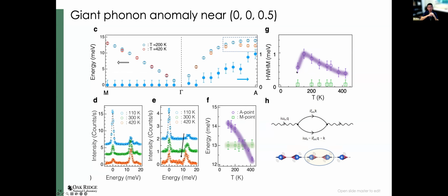So that motivated us to propose a mechanism different from a traditional Van Hove singularity-driven CDW, because first of all, the vector does not match, and also because the phonon anomaly mainly occurs at the half L peak, the 0 half L peak. So that is an indication that the phonon and the magnetism are interacting with each other and giving rise to the phonon anomaly as well as the CDW.